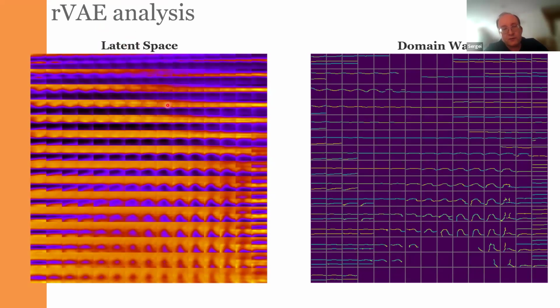And the way that we choose the descriptors is basically the squares centered at the domain walls. And now you can see that our latent space encodes the possible domain structures inside the material. So this is the region of well-defined 180-degree domain walls. This region is occupied by the needles of the domain. And these are the regions that are occupied by more complex domain structures.